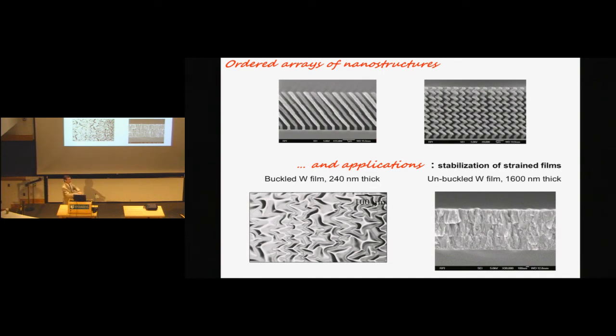This is a top view of a buckled tungsten film. Okay? And you notice that it has buckled when the film is really thin, about 240 nanometers in thickness. Okay? So these are really, really thin films. You would like to grow thicker ones. Tungsten is being used, for example, in ICs as barriers for diffusion of copper into silicon, right? Copper is the actual interconnect which is being used. So you put tungsten down to actually prevent diffusion of copper into the silicon. So how do you prevent this buckling?